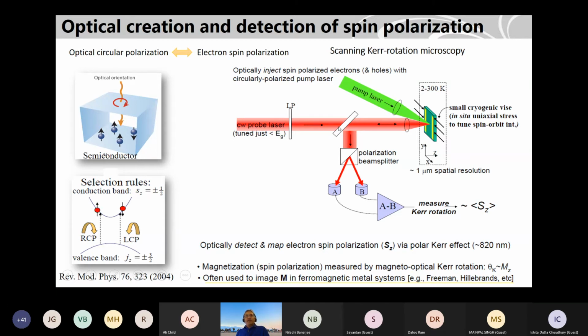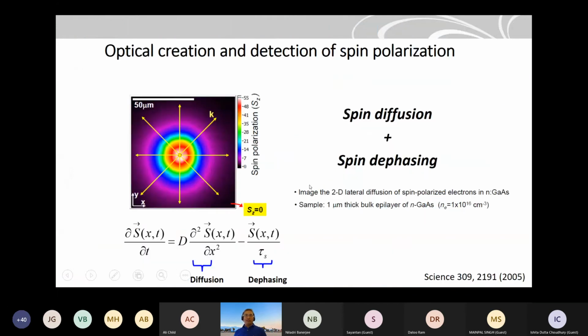And what people did was use a scanning Kerr-rotation microscopy. They have a pump laser, which creates the spin polarization. Then you also probe. This is the probe, and you split it with the polarizer here, a beam splitter, and you can measure the Kerr rotation. It's called Kerr rotation because when you have a magnetic moment in the sample or spin polarization, the signal will rotate with some angle. Why am I showing that? Because spin injection detection was not possible by all electrical methods, but with optical methods, people could see the spin polarization they create in the semiconductor, and that helped us find out how to do it with electrical methods.